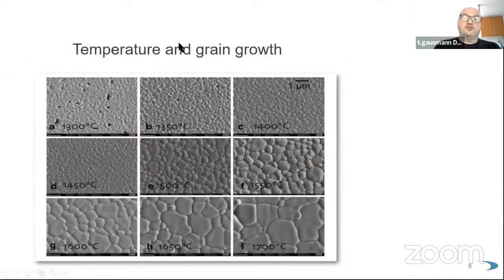Here you can see the temperature and grain growth. This is very important to know. So here you can see little black spots at 1300 degrees Celsius. These little black spots are porosities in the material. This is just a part of the material. Still here at 1350 degrees, you still have some porosities. Porosities are never good in a material. So material must always be very homogeneous. No blemishes, no cracks, no holes or whatever in it. So you can see here that at 1400 degrees, this is the minimum temperature for the material to be homogeneous. So when you look at it, the grain is growing. It's getting bigger from here to there, from left to right.